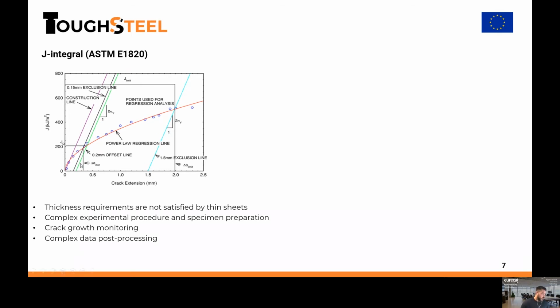Well, this procedure is quite complex. The experimental procedure is quite complex, and the specimen preparation requires exhaustive effort, as well as monitoring of the crack growth during the full test. The standard defines different methods, like the compliance method, to evaluate this crack growth, but it can also be measured with alternative systems like video or traveling microscopes, etc. As I said, the data post-processing is also quite complex, but of course you can do it. Then remember that one of the limitations of these testing methods is the thickness requirement.